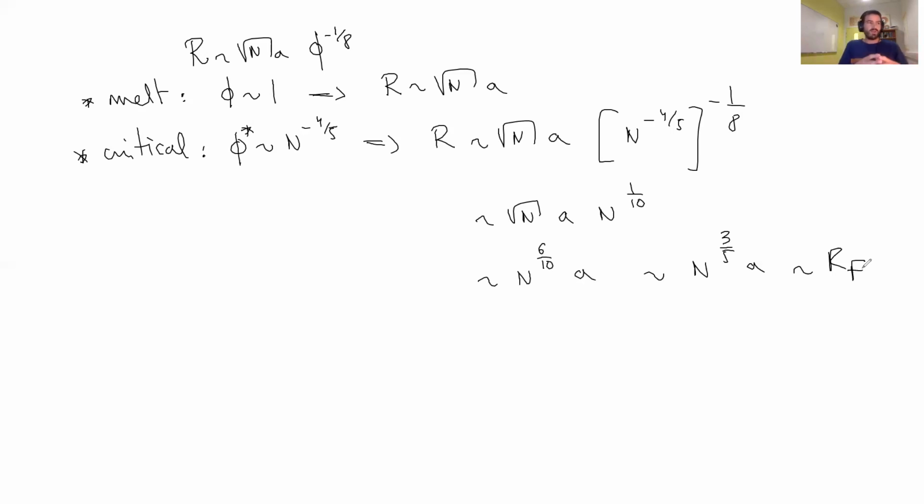So you have, for dilute solutions, a Flory scaling, for melt, a Gaussian scaling, and thanks to this blob picture, you have a full crossover in between, with a situation where you don't have a real power law, but you have a smooth crossover. Okay, that's the beauty of the blob concept.